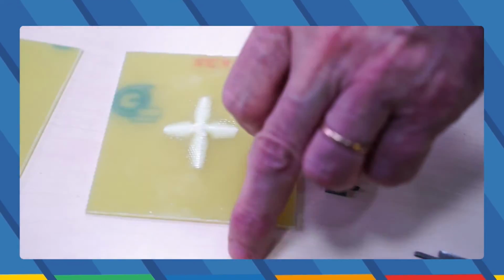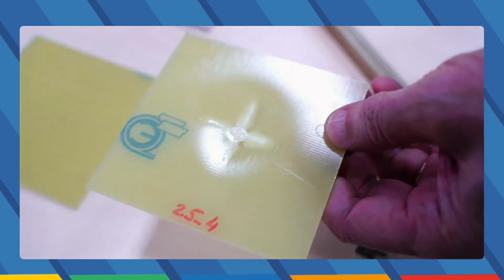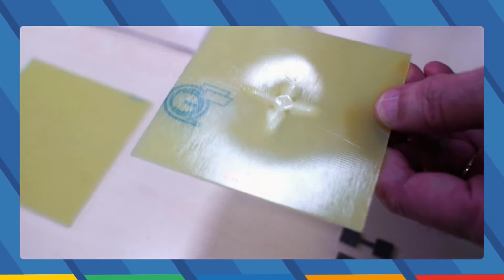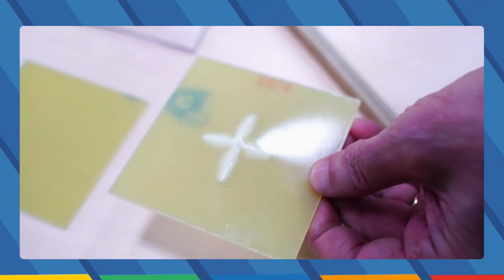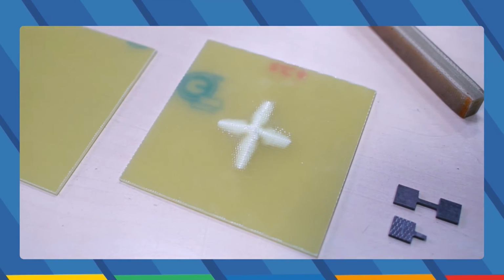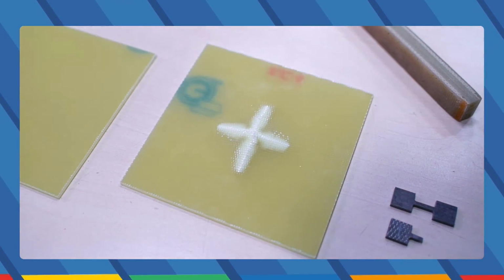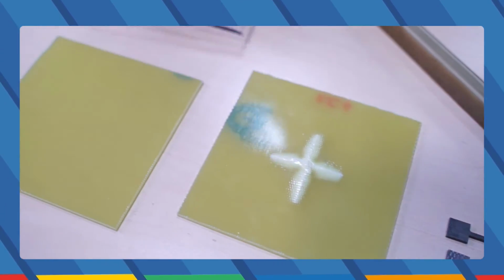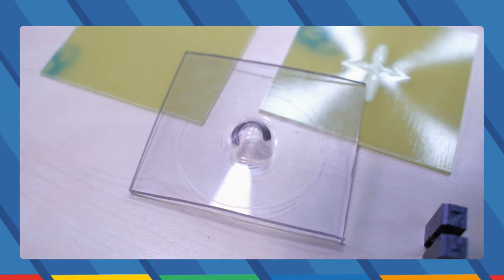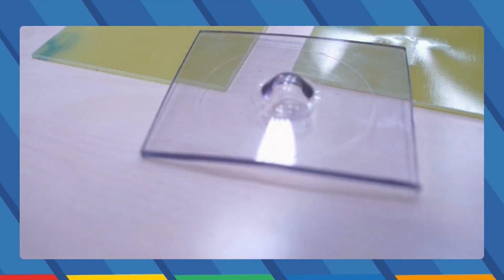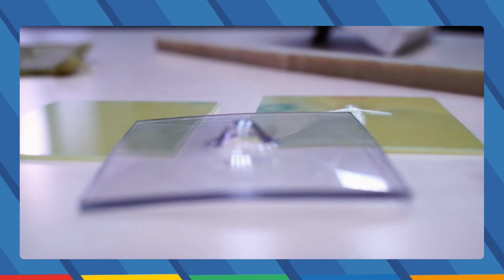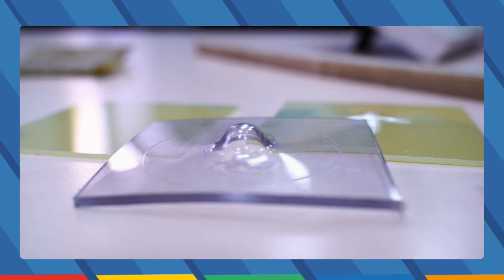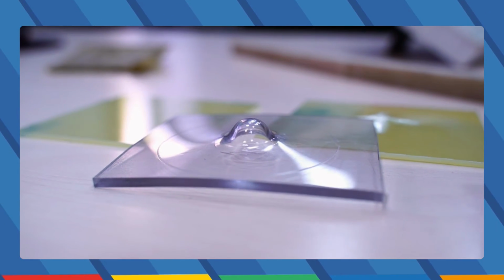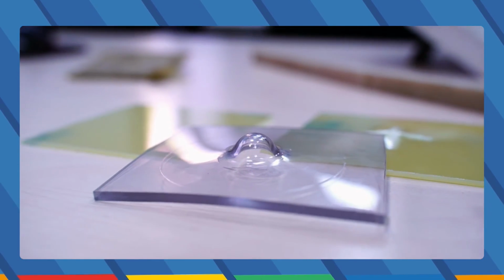And this is an impact test of composite materials with round support and then drop inside and cracks on the back side. After that we cut the sample and test it for residual strength. In this sample you can see plastic with the trace of impact and a kind of hill on the back side. This is the result of dynamic loading of different materials: metals, alloys, superalloys, composite materials, and plastic. That's all. The second experiment.